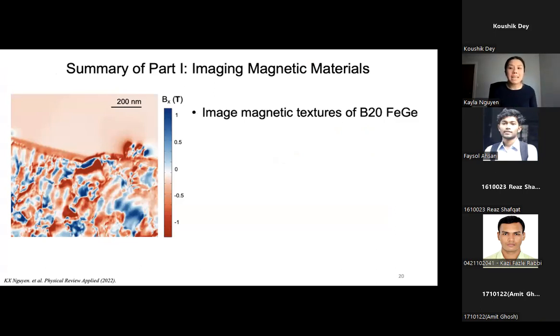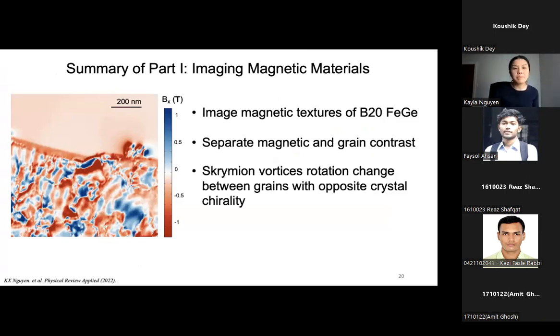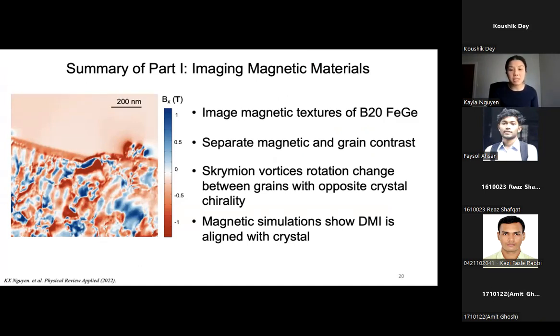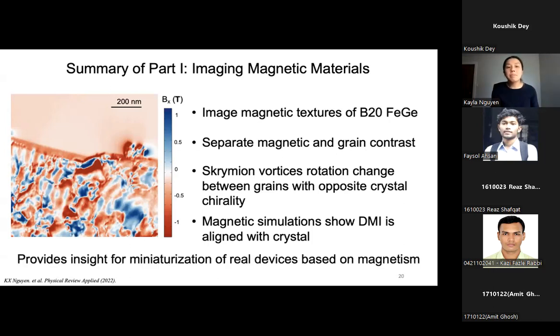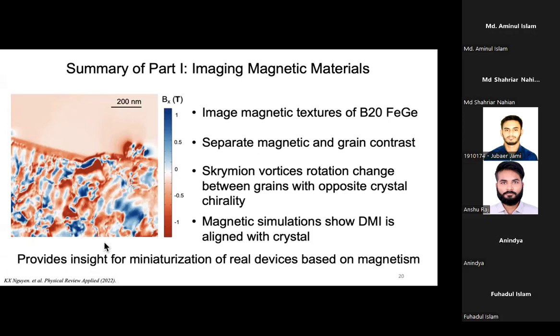We can separate magnetic and grain contrast from the polycrystalline structure. We find that skyrmion vorticity rotation changes between grains of opposite crystal chirality, and magnetic simulations show that the DMI is aligned with the crystal chirality. So magnetic simulations support our results. So finally, this provides insight for miniaturization of real devices based on magnetism. And you can find this result published this year in March in Physical Review Applied if you're really interested in reading the paper.